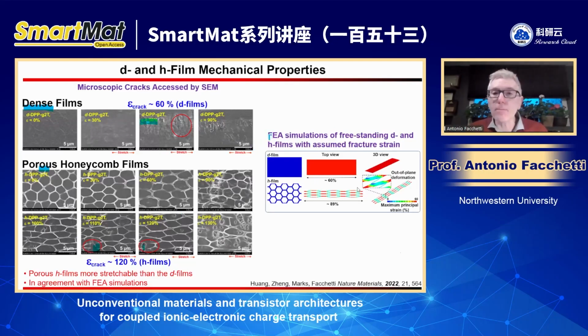And we did also computation of this by finite element analysis. And the reason why the honeycomb films are more stretchable is because you have out of plane deformation of the structure. Instead of remaining flat, it goes up a little bit when you stretch. And going up, it helps to dissipate the mechanical energy.